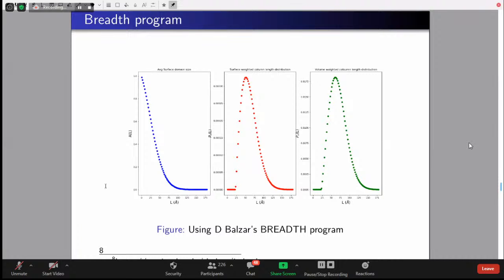Now here what we are seeing is one is surface weighted, which means it is area weighted. Over the top of the crystallites, let us say hexagonal crystallites, on the top how big they are if you see from the top. And the other one is volume weighted, the total three-dimensional volume of the crystallite, how it is varying. So in both cases you can get it from the Warren-Averbach method.